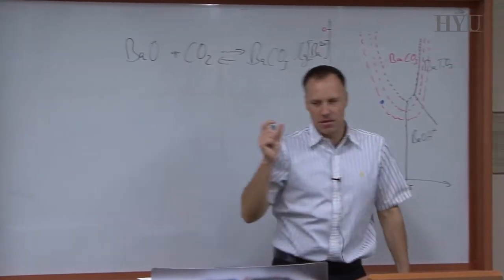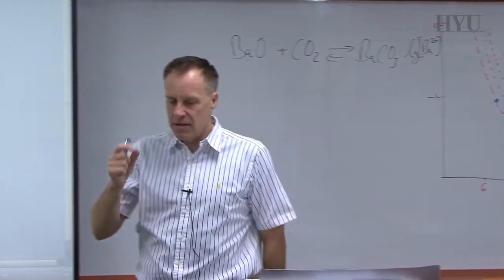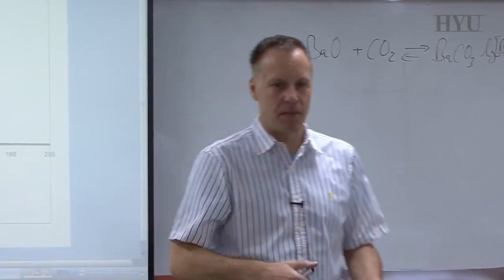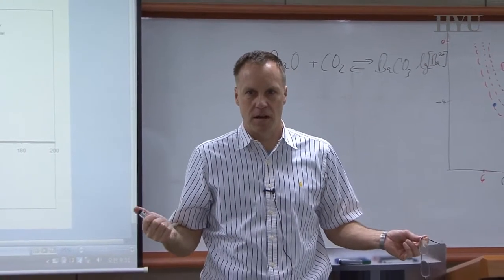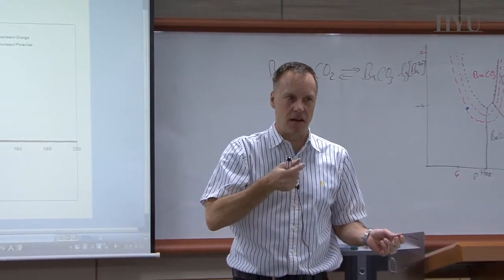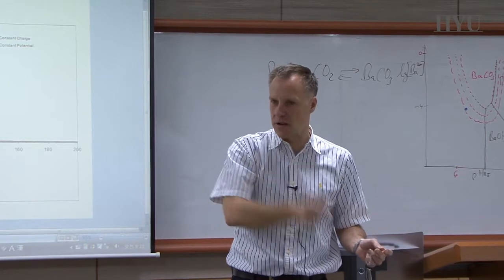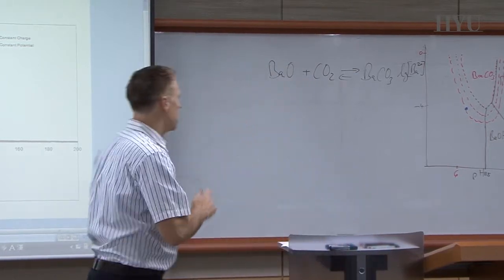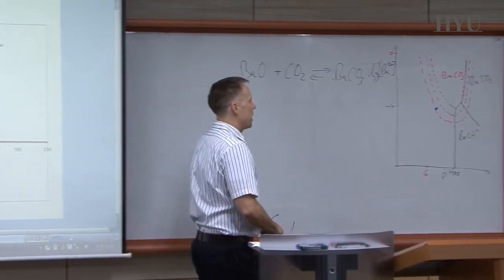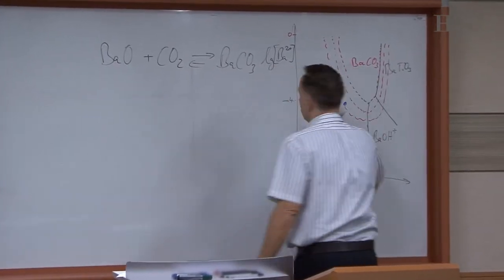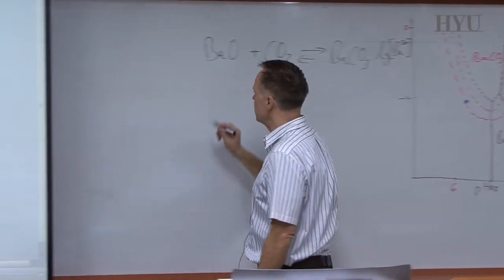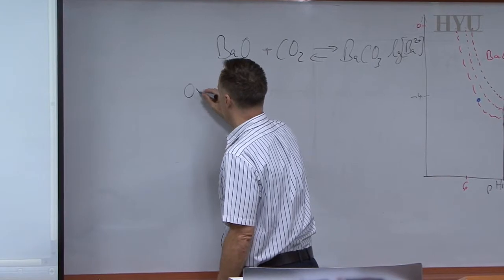Okay, so that's why barium carbonate is happening in the system, because there's carbon dioxide in the atmosphere when you work in water, but it's not intended, and typically they don't go the pure carbonate route. So what other things can we do? Barium carbonate is one possibility, but there are other salts that are really insoluble, and one of them is oxalic acid.